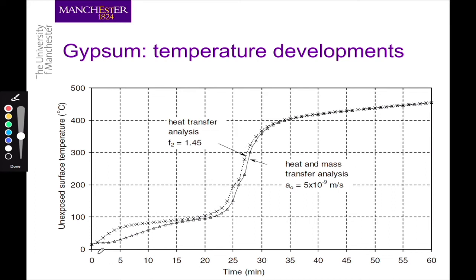Well, let's look at how gypsum performs as a fire protection material. This, for example, is a piece of gypsum, and what we have in here is the temperature of the gypsum on the unexposed side as a function of time. As you can see, there are two distinctive stages of temperature rise. One is this stage, where the temperature barely increases beyond 100. 100, of course, is the water evaporation temperature. And afterwards, there's this stage of rapid increase because of the highly conductive performance of the material. So we have to look into these aspects.